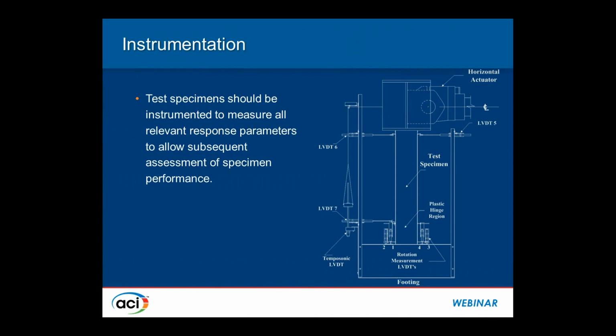On this slide, you see vertical LVDTs placed within the plastic hinge region, and this plastic hinge region obviously is not known accurately, but there is a bit of a discussion given in the document on that, the fact that it does vary anywhere between flexural depth over 2 to the entire flexural depth for beams and columns, and for shear walls it can be smaller, or it can occupy the entire floor height sometimes. So this has to be well thought of depending on what member you are simulating.